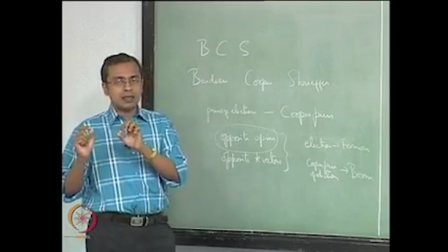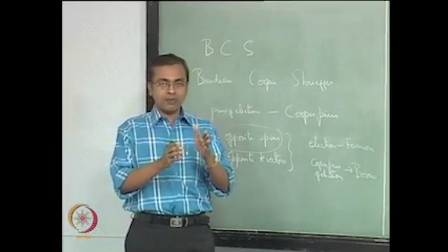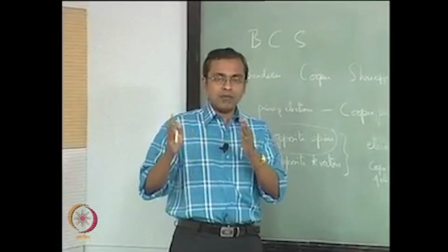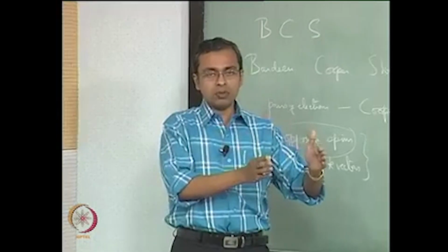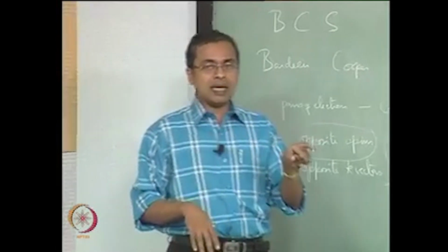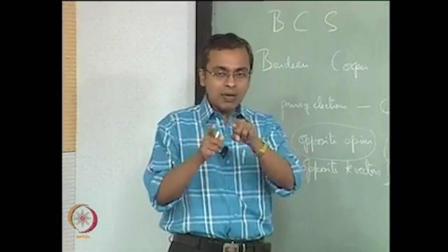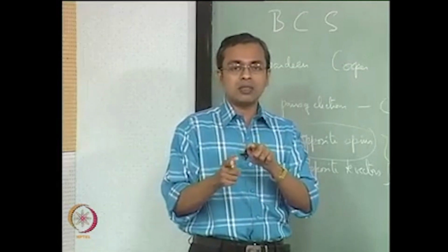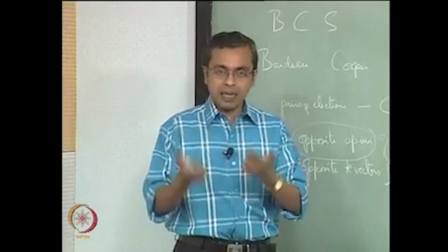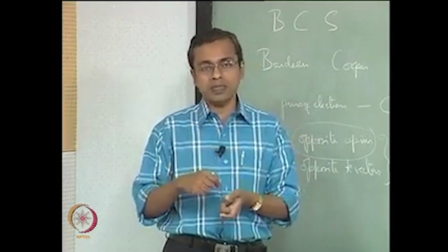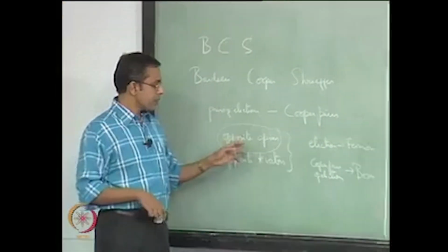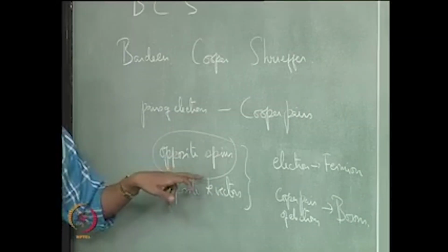To repeat it, magnetism requires spins of electrons to align themselves so that you get the magnetic moment in one particular direction. So if magnetism is interfering with superconductivity, and if you raise the magnetic field strength you break down superconductivity, it conveys the idea that the aligning of spins is not desired in the superconducting state. This can be taken one step further to say that perhaps deliberately aligning them in the opposite way is what superconductivity requires, and that is what is captured in this Cooper pair, the fact that this Cooper pair takes in electrons of opposite spins, okay.